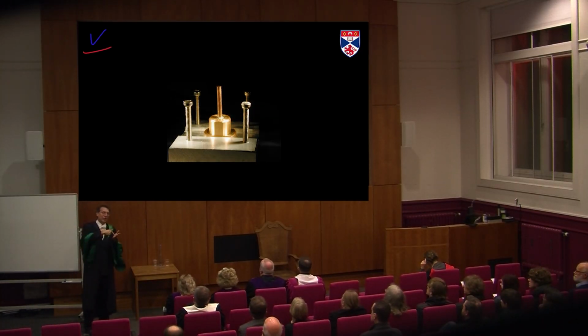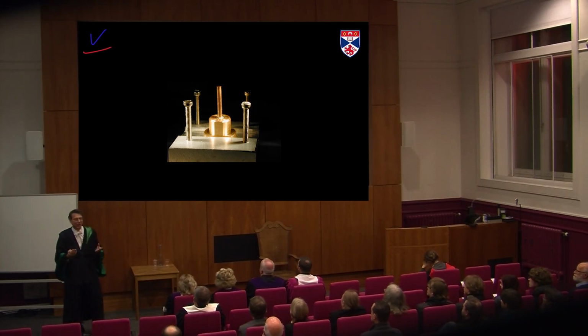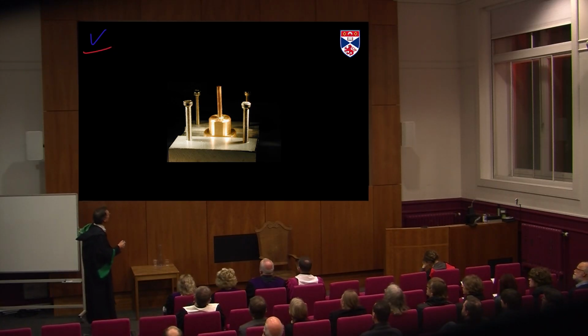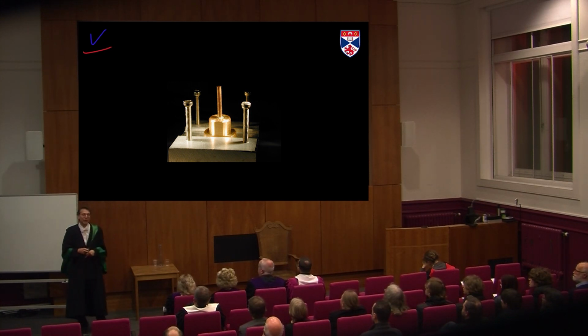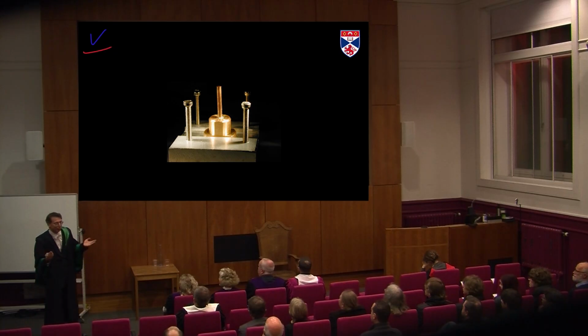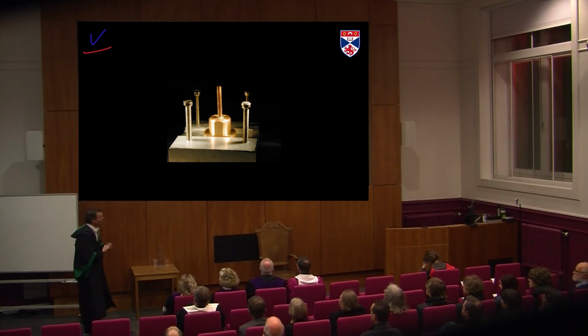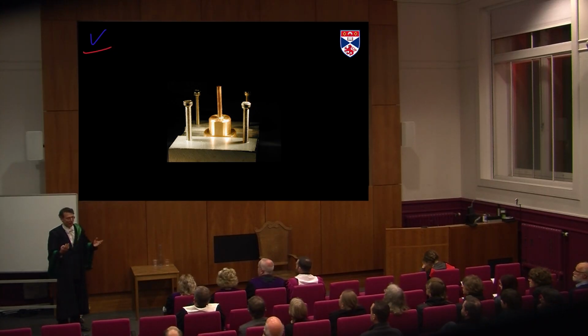Okay, how do we get the surfaces of these samples? I told you we bring a tip very close to a surface. We need to somehow prepare the surface. It's a very archaic method by which we normally prepare these surfaces. So here is a sample. We glue a rod on top. That's this rod here. The sample you can hardly see because it's this very small thing here. And then we just knock the rod off. And then we hope that it takes away some part of the sample. And if we are lucky, that gives us an atomically flat surface. It doesn't always work, but it works sometimes.